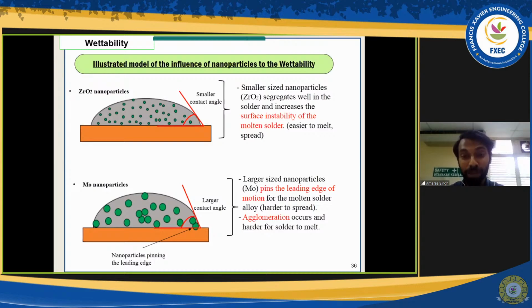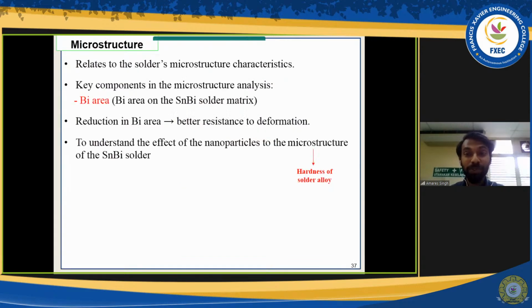I found out some agglomeration in the microstructural properties. Earlier I mentioned that the microstructural properties seem like a subjective area. How do we know if the grain is being reduced in size? Since our solder is tin and bismuth, I've taken the bismuth area, because from EDX analysis I can distinguish the difference between the tin and the bismuth area. So I've taken the bismuth area to be calculated.